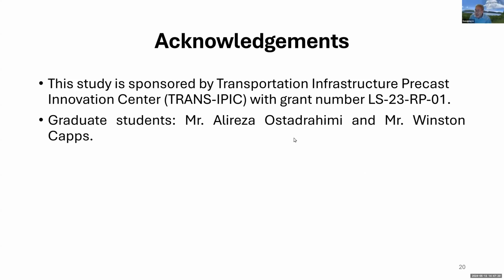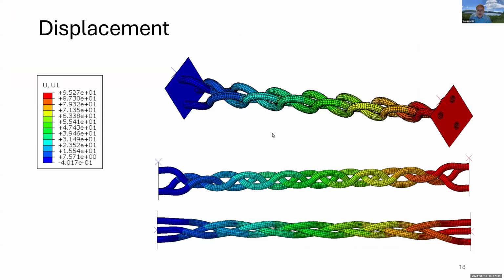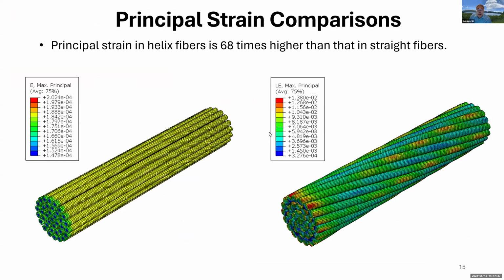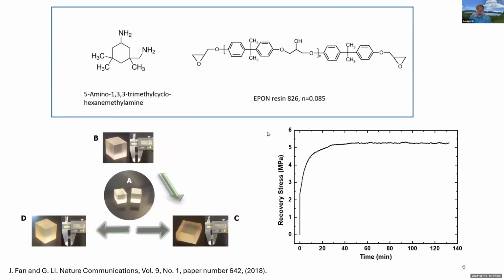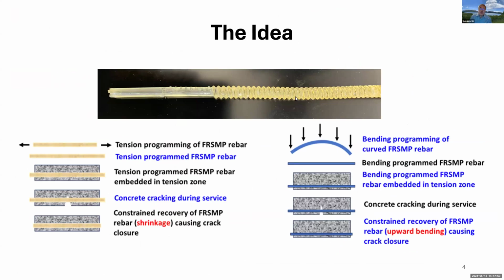Yes, just the expectation. Before I go to that step, the first question we need to solve is the interfacial bonding between the FRP rebar and the concrete, because thermoset polymers usually have very poor interfacial bonding. That's why, when we prepare the conventional polymer-based FRP rebar, we make some grooves to improve the surface roughness so that there is some interlocking with the concrete.